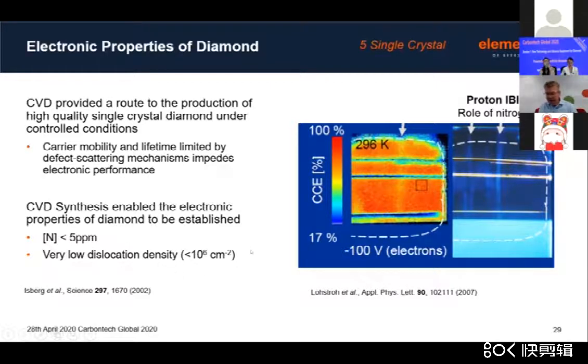And you need very low dislocation densities, if you can get them below around 1 million defects per centimeter squared. And when you do that, you get very high mobilities of electrons and holes in the material, and you have very good insulating properties. And then around 2007, a very nice experiment came out that really showed the role of nitrogen. This is looking at luminescence of a cross-section of CVD diamond on a substrate. And what you're looking at here are layers of nitrogen dopant introduced at around 20 to 30 parts per billion.